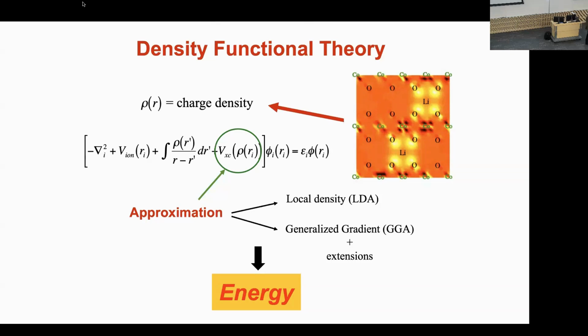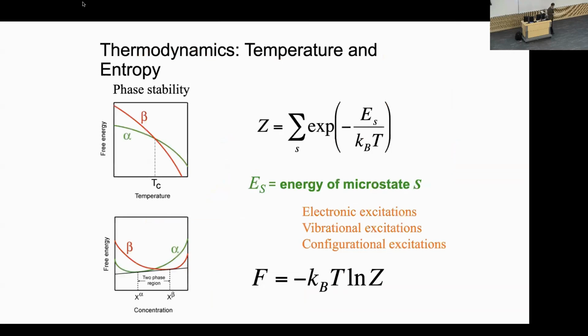The only thing to take away from this is, if you have a crystal structure, you know which atoms, you put them in position somewhere, and then you can calculate its fundamental properties. For example, the energy of this crystal structure, its charge density, which gives you some sense of how the ions are bonded together, and other properties like elastic moduli. So very fundamental properties that we can calculate with density functional theory, but they're really 0 Kelvin properties. What we also want is to be able to predict finite temperature properties. For example, if we're interested in phase stability, either as a function of temperature or composition, we need free energies. And to connect the electronic structure to these free energies, we have to rely on statistical mechanics.